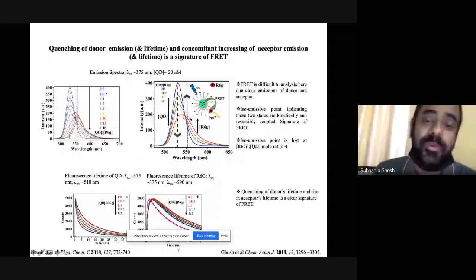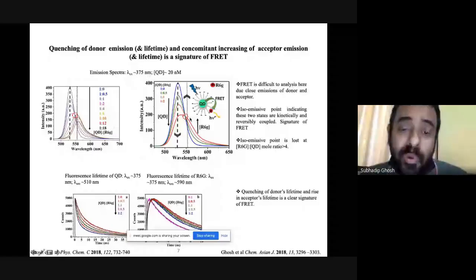at the cost of increasing the emission of the acceptor, which is the signature of FRET. Now, when I normalize the area under the curve, it shows there is an isoemissive point between the emission peak of donor and acceptor. This isoemissive point indicates that donor emission is coupled with acceptor emission and they are in an equilibrium process. So if X amount of emission is going from the donor side, the same amount of emission will be received at the acceptor end. And that is the reason behind this isoemissive point arising. This isoemissive point is very interesting here and indicates this is FRET.